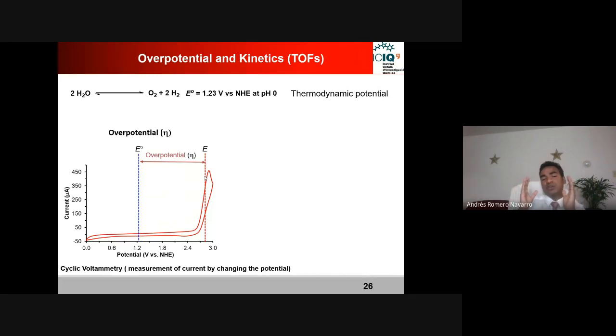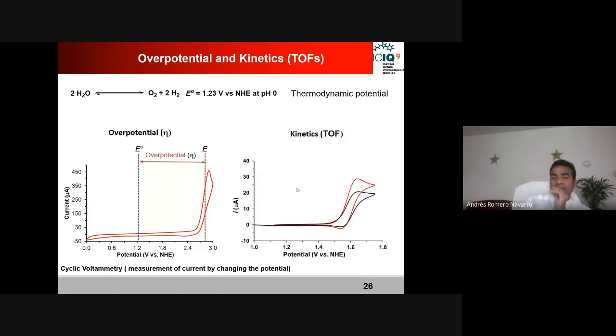So then imagine that if we want to design a molecular catalyst, if the overpotential is low, then we can say that catalyst is good, and the best. So our goal is to design a molecular catalyst which has as low an overpotential as possible. And the second is the kinetics, that is turnover frequency. We can also get this information from the cyclic voltammogram. For example, this black one is showing a current which is relatively low, and the red one is showing a current which is relatively high. And imagine that those are under identical conditions. So whichever is giving the higher current is doing the reaction faster. It means that it is giving the higher turnover frequency.